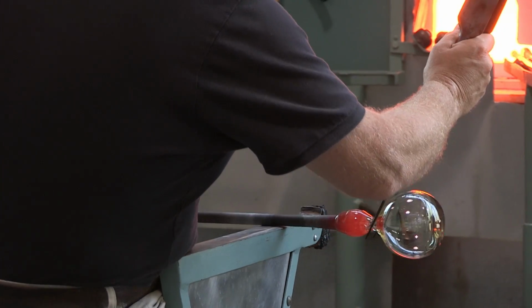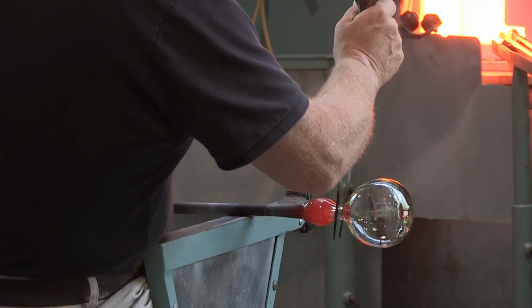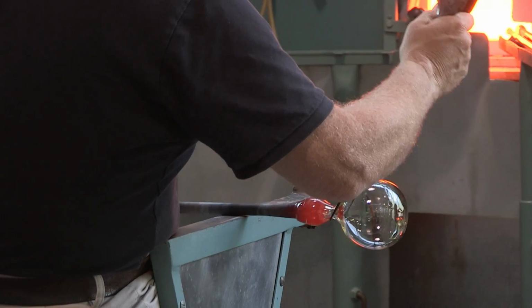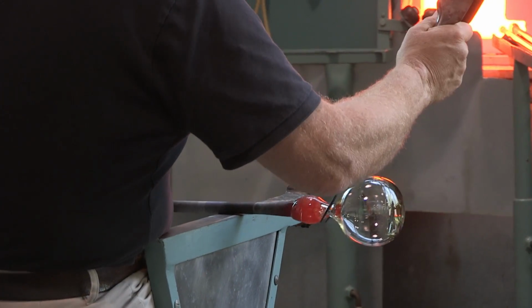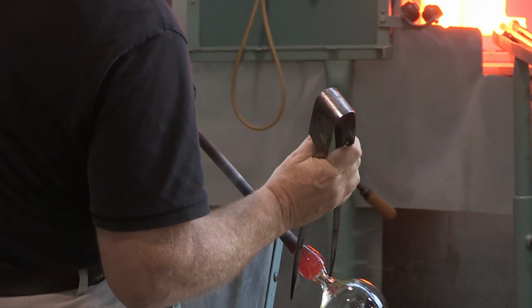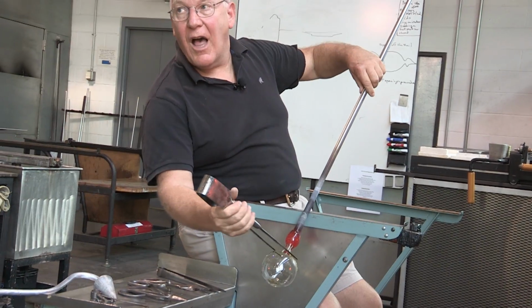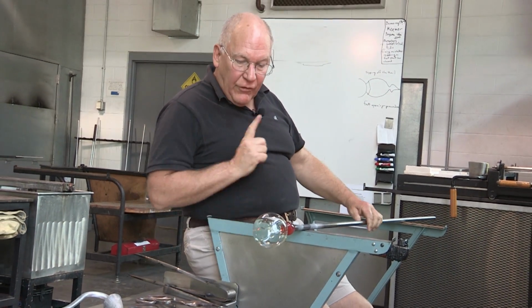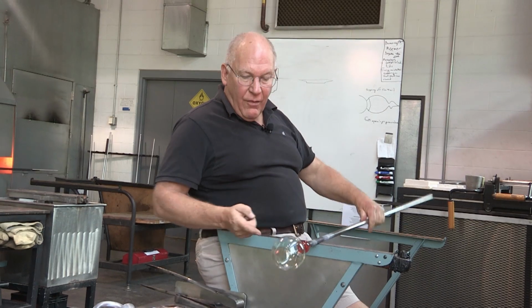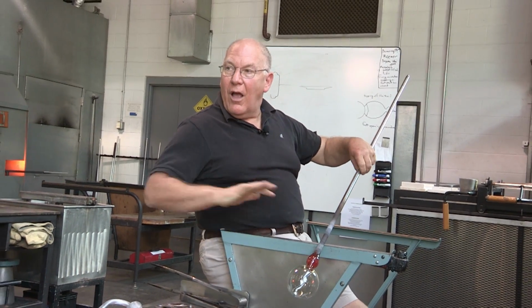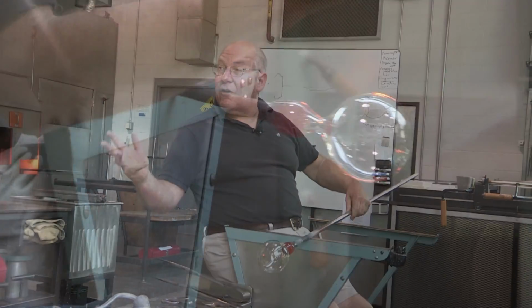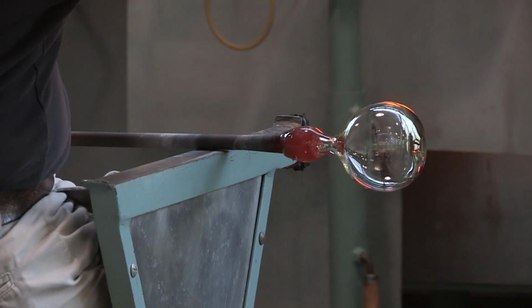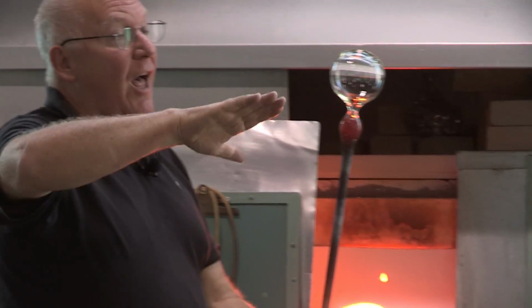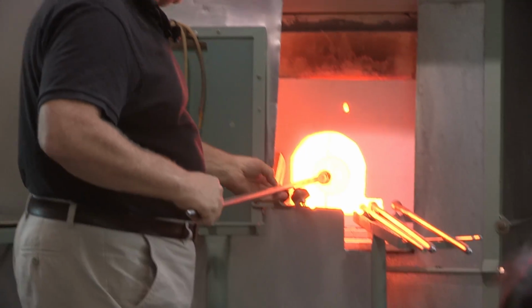It's essential, whatever you're making, whatever the decoration, it's essential to make a really good skinny neck, small diameter neck with tapering concave shoulders. The skinny neck will break easily. The concave shoulders are utterly resistant to thermal shock. So when you transfer it to the punty and do that first reheat, it'll never crack. If the shoulders are convex, it'll crack every other time.